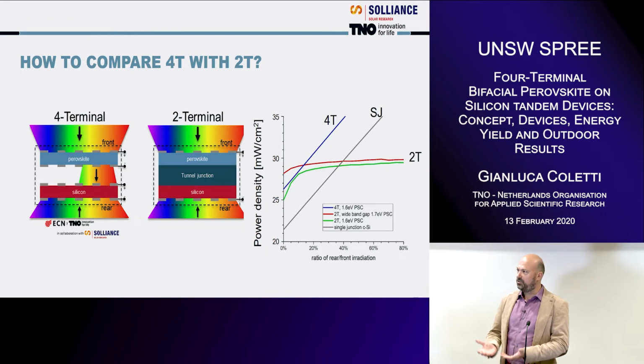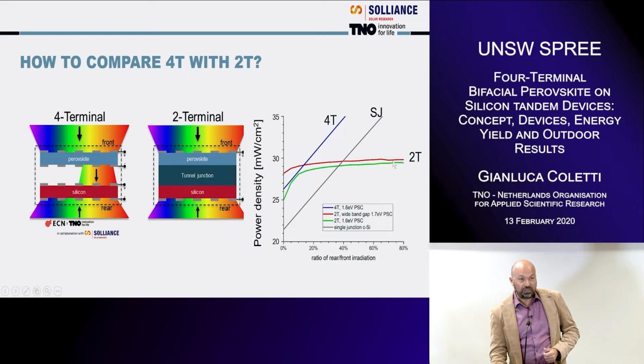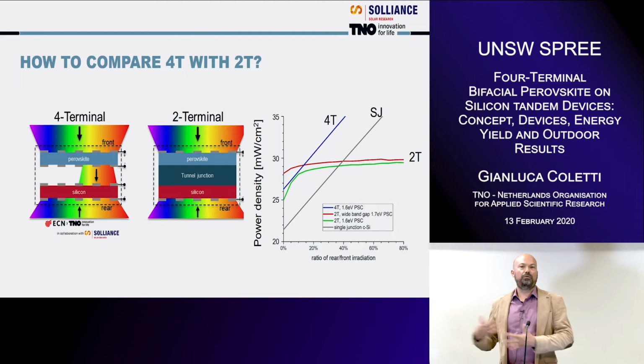But you can design the top device differently. You can increase the band gap. You can make it thicker. You can have different modifications here. You will still have your capping, but as you see in this case, and consider here we are comparing 1.6 with 1.7 electron volts, you generate more power, but then it depends on how much the rear irradiance is, that would change. So you could design a device that is probably ideal for 10%, 5%, which starts to add some complication from the manufacturing point of view, but still it's a gain that comes basically for free.